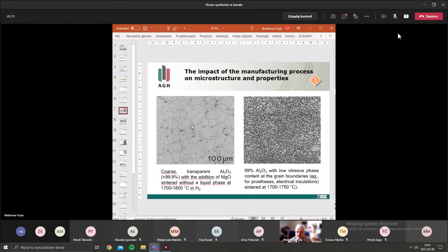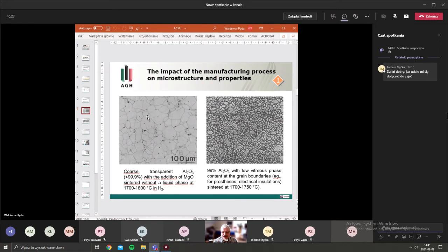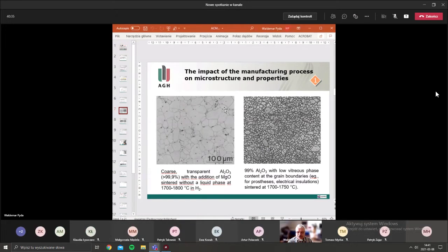Each microstructural feature matters. Okay. Large grains, a small amount of pores, small pores, small porosity, and clean grain boundaries, pure grain boundaries with no additives. Only magnesium oxide can be detected in the grain boundaries. Coarse grain microstructure and some transparency is obtained. In the right case, smaller grains, very thick grain boundaries, composed of glassy phase, hinder the transparency of this material.